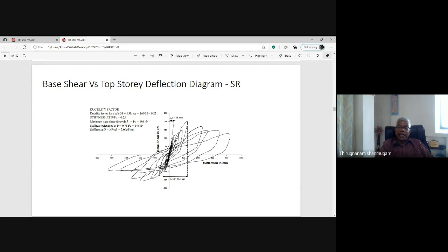The load deflection diagram is like this. That is a hysteretic diagram. From this load deflection diagram, we are calculating the ductility factor as delta U by delta Y. For example, in the 31st cycle, delta U divided by delta Y gives a ductility factor of 9.22. And the stiffness is taken from a tangent drawn at the 0.75 PU level, P equal to 0.75 PU. The slope of the tangent gives the stiffness value. The maximum force is 198 kN at the level of these 31 cycles, and 0.75 PU is 148 kN. The stiffness calculated as the ratio is 7.4 kN per mm.